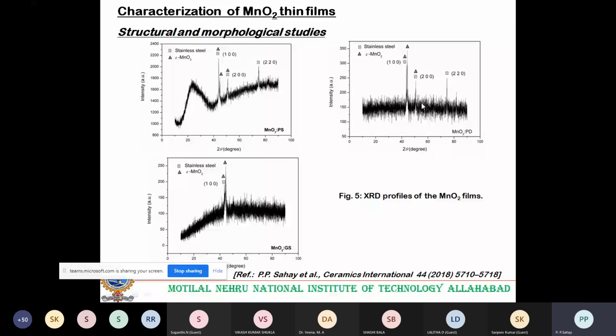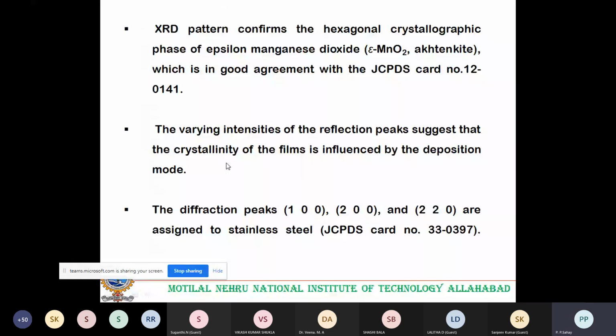So what we do, we look for certain peaks especially for the MnO2. Here there is only an MnO2 peak. Here also there is an MnO2 peak, independent, no overlapping. Here also one independent peak, but still there was a doubt. So what is the XRD result I mentioned? XRD patterns confirm the hexagonal crystallographic phases of epsilon manganese dioxide, which is in good agreement with the JCPDS card number, this one. This is a normal practice.